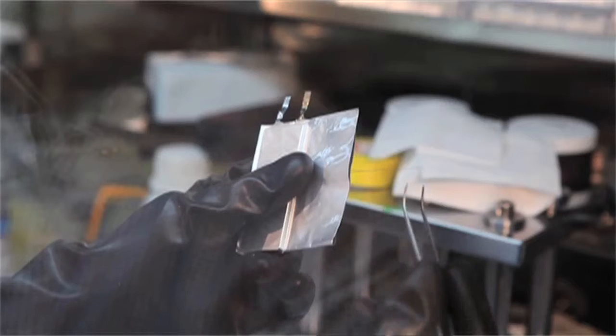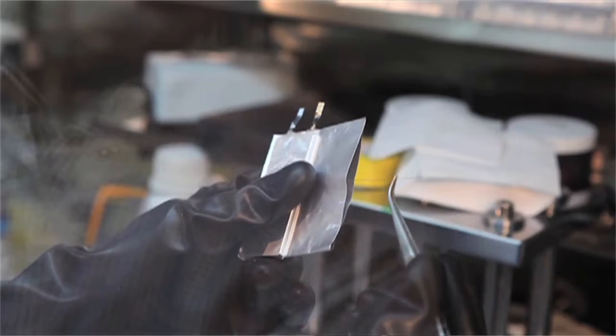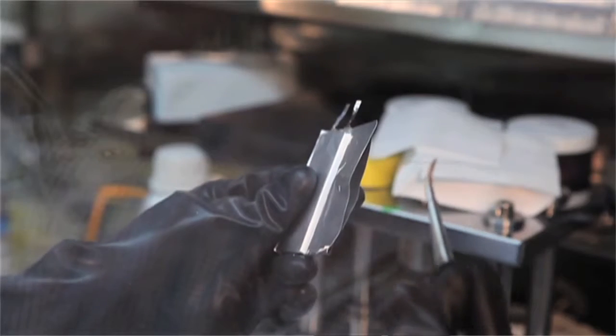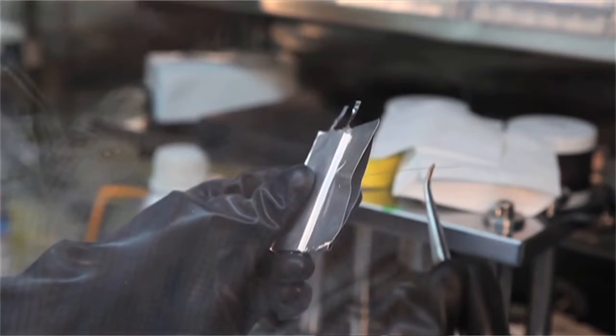A fiber optic sensor is thin like your hair, only about, depending on what type, 80 microns or 100 or 150 micrometers thick. That is a sensor which you can really, and the fiber itself is a sensor, and that is a sensor where you can really realistically place between the electrode stacks in a type of lithium ion battery in order to extract information.